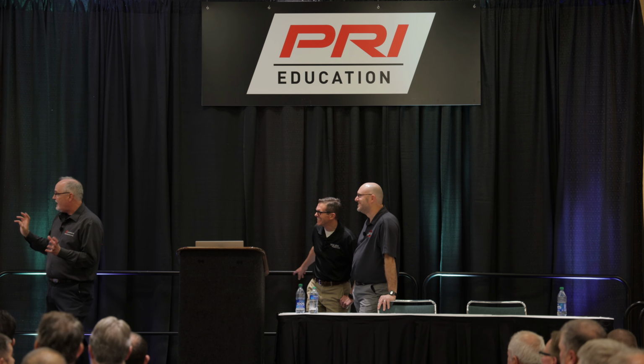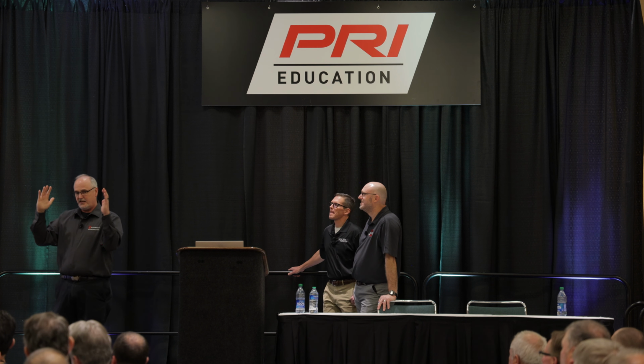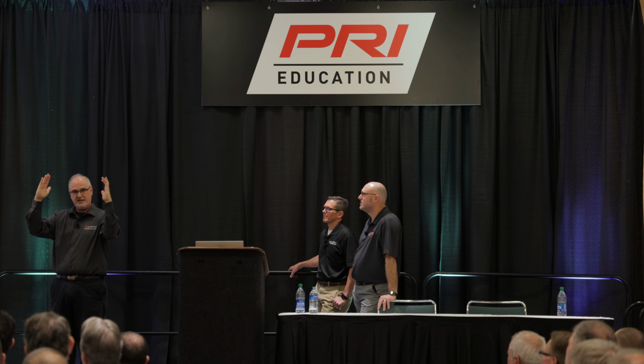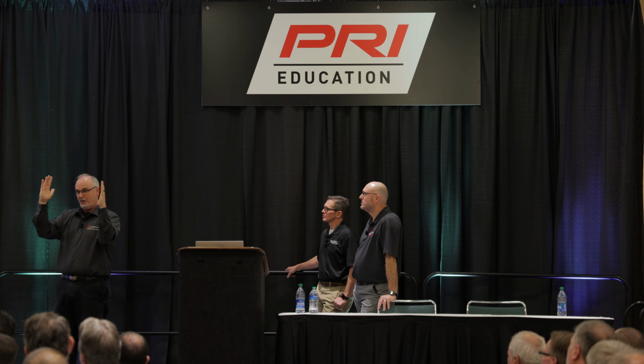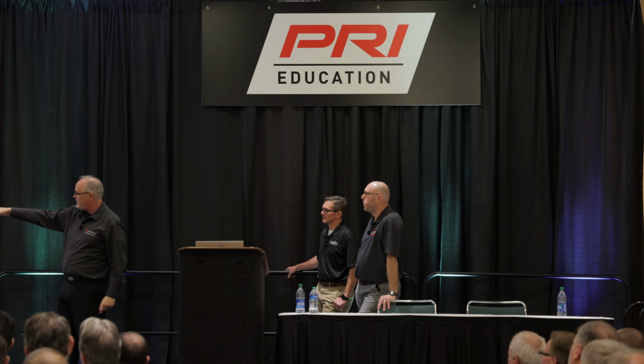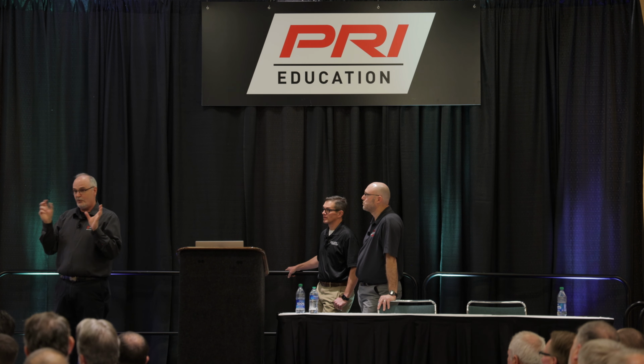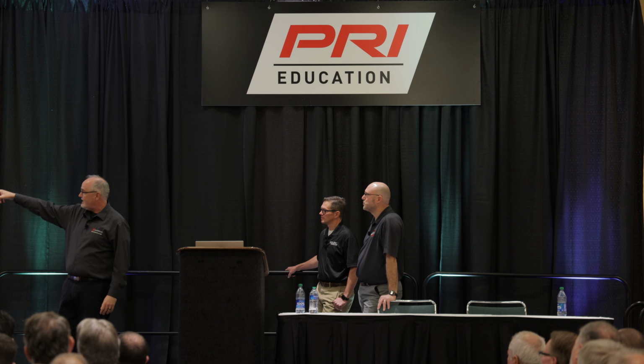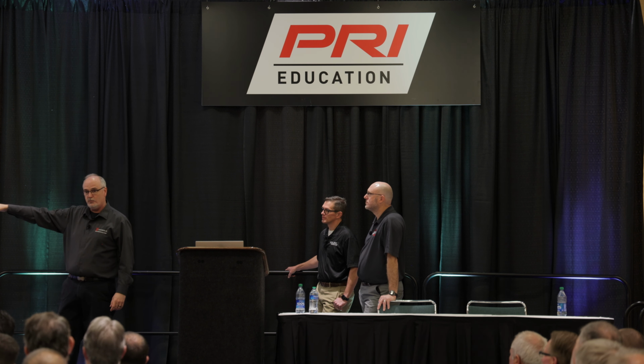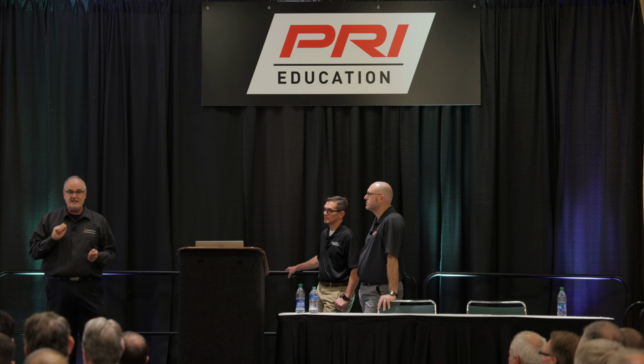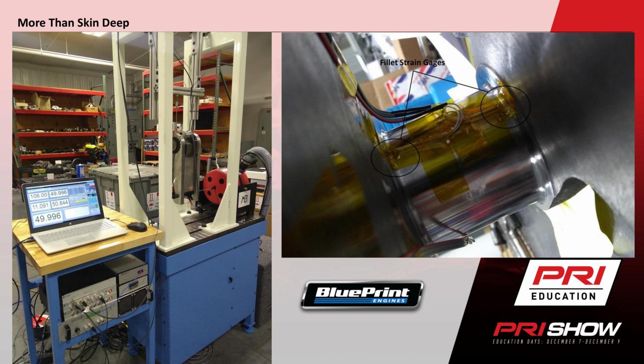So what they did is they had some people come up with this deal that has like 2 tuning forks. It's 2 big steel plates on a crank, and they cut a section on it. They bolt these on it, and they drive it with about 1,000th of deflection at real high frequency. And it creates that same stress in that fillet that you would get in a running engine. And they can correlate back and forth from cylinder pressure to how they drive this tuning fork to actually model exactly what's going on. And it's just a cool piece because they go in here with all the strain gauges, make sure it works. And there it is over on the left.